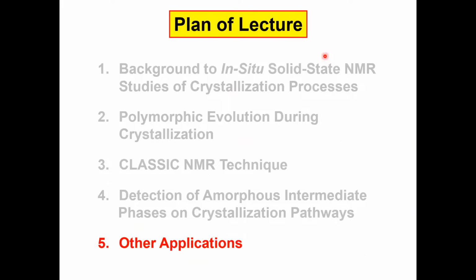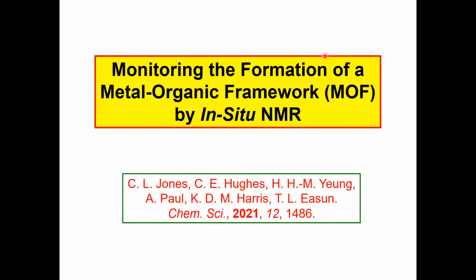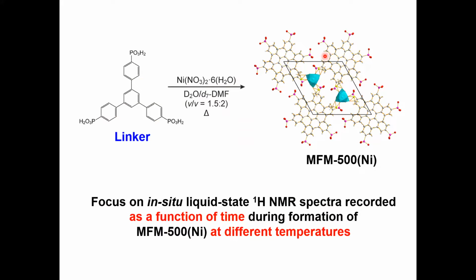So I want to conclude in the final minute or two with a couple of other areas of application. More recent work here looking at the formation of a metal organic framework by in situ NMR. And a particular example is shown here. This particular linker, when reacted with nickel nitrate, produces this MFM-500(Ni) MOF containing nickel. And although we had carried out a classic NMR experiment, I'm going to focus on the liquid state proton NMR component of that classic NMR experiment. We're going to look at the proton NMR spectra as a function of time at different temperatures with a view to gaining kinetic information on the MOF formation process.